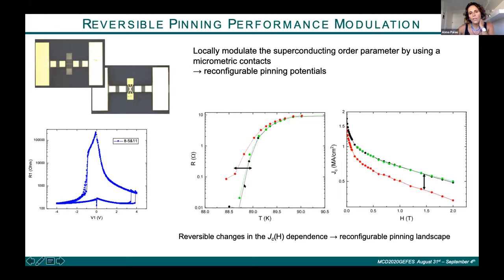We have measured the resistance, the TC, and also the JC of one bridge before, at the starting point. And after inducing switching to the low resistance state here in red, we reduce the TC and also we infer the pinning performance of the material. This is the critical current density as a function of the magnetic field. And we observe that the critical current density can be reduced.